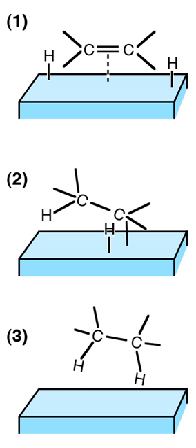Consequently, contact with a hydrogenation catalyst necessarily causes cis-trans isomerization, because the isomerization is thermodynamically favorable. This is a problem in partial hydrogenation, while in complete hydrogenation the produced trans alkene is eventually hydrogenated. For aromatic substrates, the first bond is hardest to hydrogenate because of the free energy penalty for breaking the aromatic system. The product of this is a cyclohexadiene, which is extremely active and cannot be isolated. In conditions reducing enough to break the aromatization, it is immediately reduced to a cyclohexene. The cyclohexene is ordinarily reduced immediately to a fully saturated cyclohexane, but special modifications to the catalysts, such as the use of the anti-solvent water on ruthenium, can preserve some of the cyclohexene, if that is a desired product.